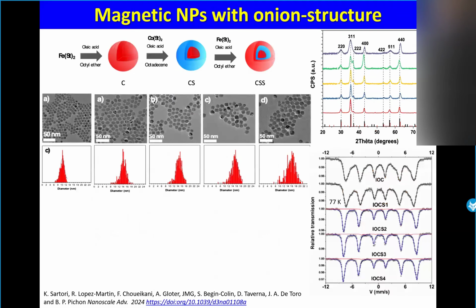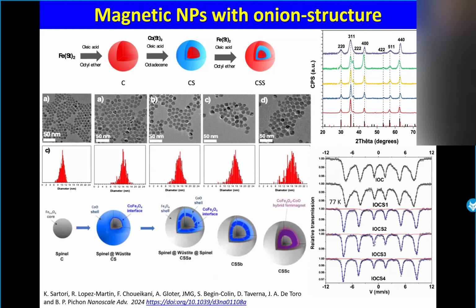Here, another concept is to create onion structures. We have a nanoparticle, we recover it with one layer, then with another layer, and we follow the evolution of the magnetic structure and the magnetic surface anisotropy. So you have some references.